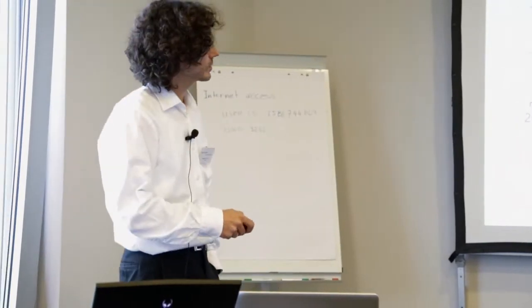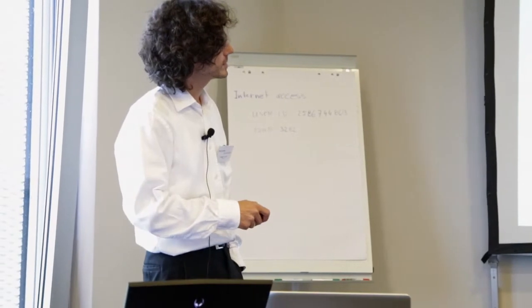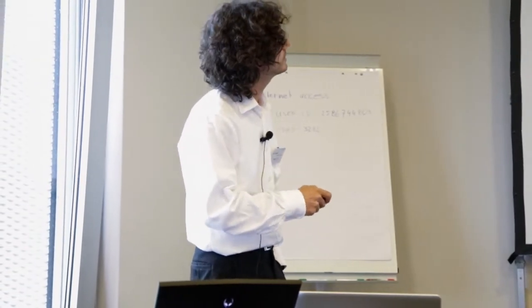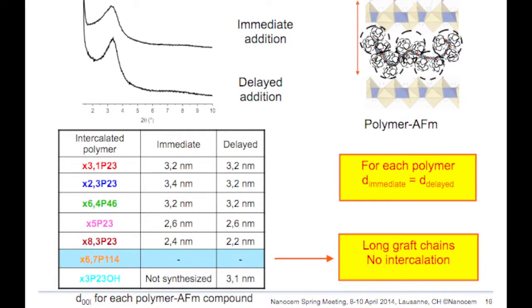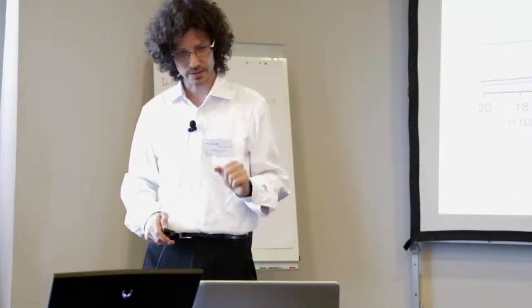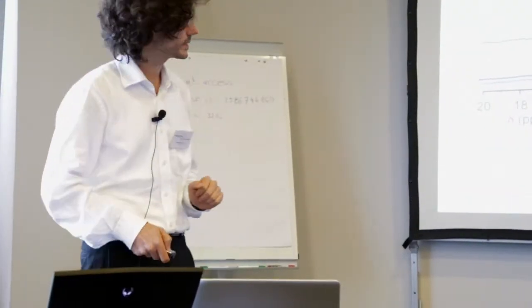So what you see on this graph is for 3 different polymers that there is a clear shift in the aluminum NMR spectrum, which is indicating that you have an intimate interaction between the polymer and the aluminate phase. What's more interesting is that you have exactly the same shift if you do this in delayed addition. So whether the polymer is present during the precipitation or added afterwards, you get the same result. That is an important result here.